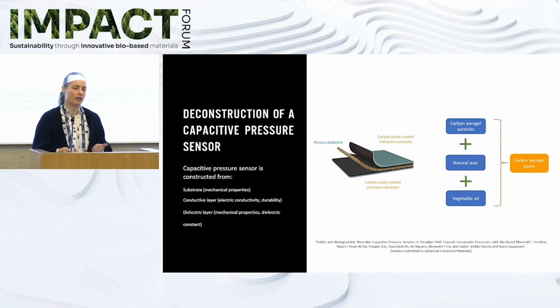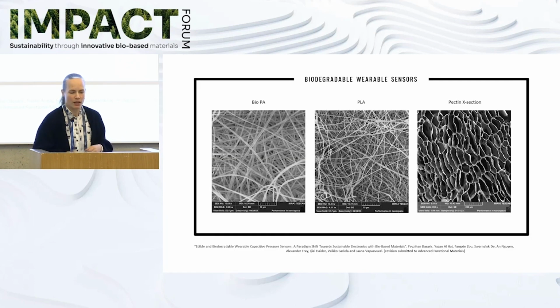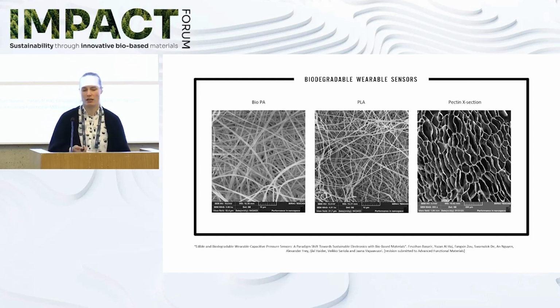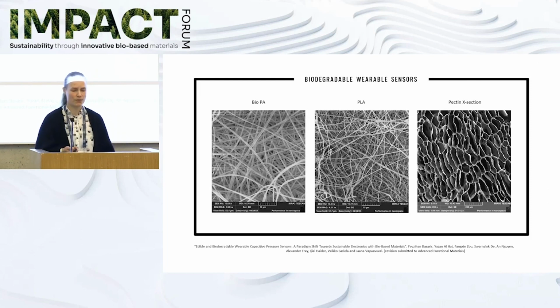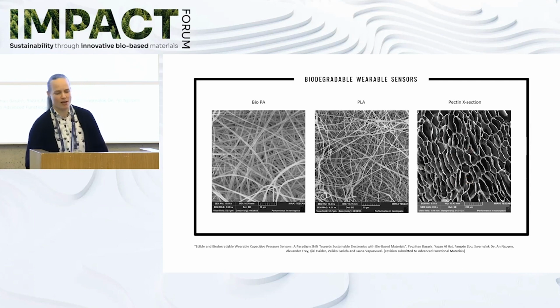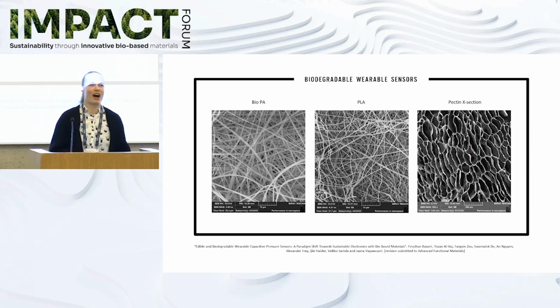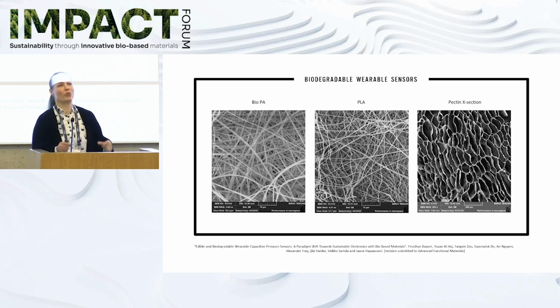And then the remaining task was pretty much how to optimize the dielectric layer in between. Here we had a few different bio-based alternatives, and out of these, we were the most interested in these fruit peel-derived pectins. And here you can see freeze-dried anisotropic cryogels of the pectins that actually worked quite nicely in these wearable pressure sensors.